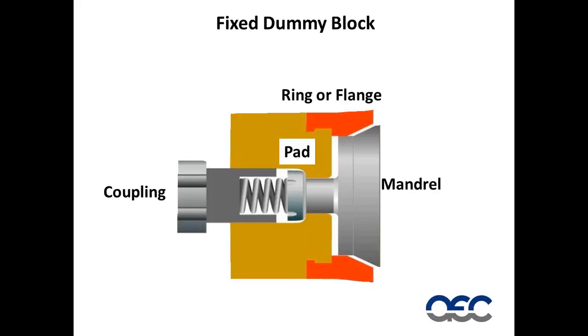If we dissect the dummy block, we have a few components. We have a mandrel, which we use to push back into a ring or flange to expand the dummy block. We have a pad area that supports the mandrel when it's pushed back, and we have a coupling that attaches the fixed dummy block to the stem. We also have an angle between the mandrel and the flange or the ring. These angles are anywhere from a minimum of about 20 degrees to a maximum of 35 degrees. And typically we have anywhere from half a degree to 1 degree difference between the angle on the ring or flange and the mandrel. We also have a gap between the back of the mandrel and the pad area, and it's the movement of the mandrel within this gap and the amount and steepness of the angle that give us our expansion.